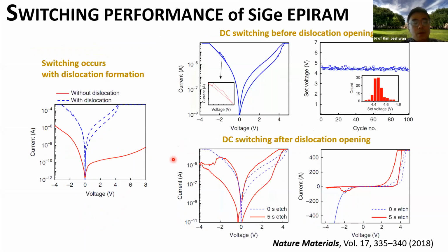As you can see, if we do not have any silicon germanium with dislocation, switching behavior is not observed. But by growing the relaxed silicon germanium on silicon, we are able to have switching. This switching behavior is extremely stable, and variation is very, very low. But the on-off ratio is kind of low, so we also did some treatment where the etchant can widen up the top part of the dislocation. Then we are able to get a higher on-off ratio as well.